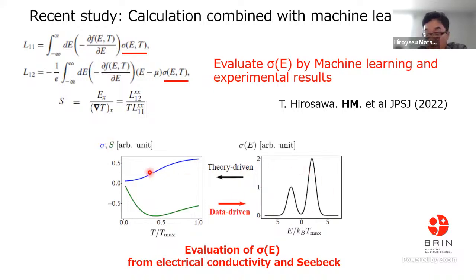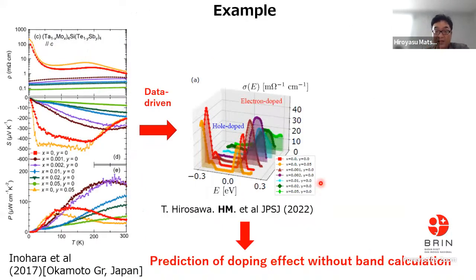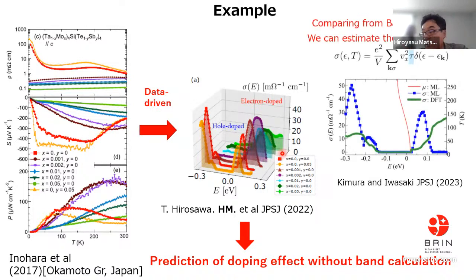This is the theory-driven study. But by using machine learning and experimental results, a data-driven study, we can get this sigma. This result is the first trial result, and by using the experimental results and data-driven studies, we can get these sigmas. Using this, we can predict, for example, the temperature dependence of the Seebeck coefficient without band calculations. And by comparing with the band calculation, we can get tau directly. This is a new method that we made.